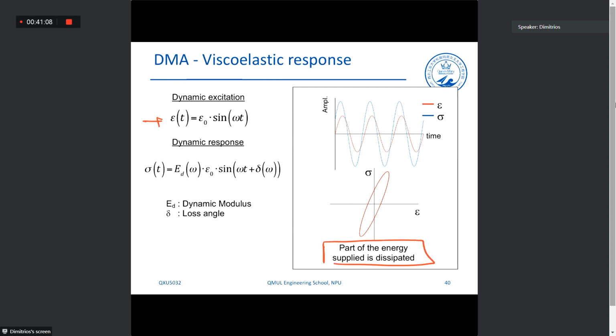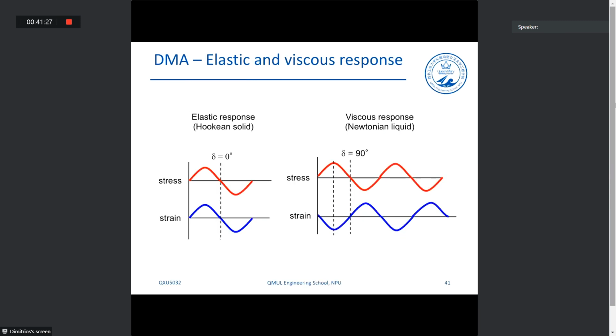We again provide an excitation, and the response is given as a function of the loss angle. And this loss angle is essentially providing the tan delta versus temperature graph, which gives us the glass transition. So yeah, for an elastic response, we can see that the angle between the stress and the strain is 0. For a Newtonian liquid, for a viscous response, essentially, we have the two of them being out of phase.